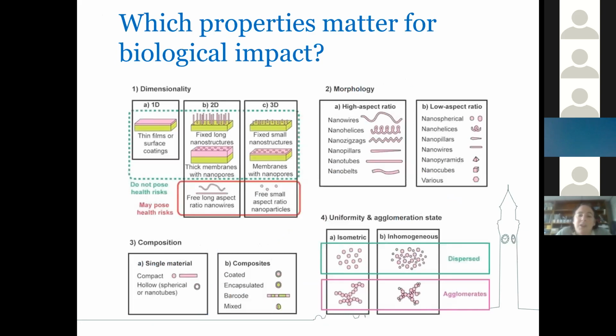The first property could be the dimensionality. I talked about whether they're one-dimensional, with a thin surface, whether they're two-dimensional, for example where they have spikes coming out of a surface, or potentially three-dimensional, with membranes or nanopores or things like that. And whether they are long aspect ratio, such as nanowires, or small, low aspect ratio, such as particles, will matter a lot. The idea is that if they're embedded or stuck on a surface, they will generally have less hazard and less risk than if they're free and therefore inhalable, or can pass into the body through the digestion system or through the nasal passageways or things like that.